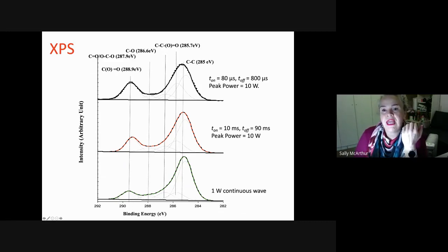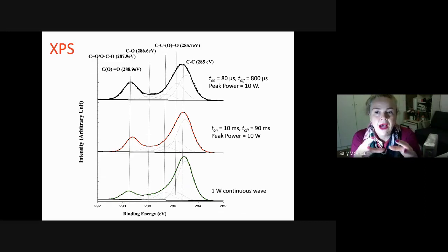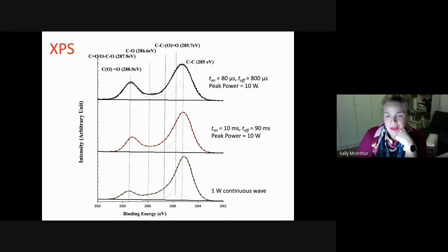And then if we go to, again, the peak power of 10 watts, but now we work in a microsecond regime, and we go for 80 microseconds on, but 800 off. So a very short burst of power and a long time for all of that energy and the reactive species to react and actually form a polymer on the surface. You can see, again, the introduction of a higher contribution in this domain that we're associating with anhydride-like species in the system. So this definitely tells us that there is a significant difference with how we pulse the system here as well.